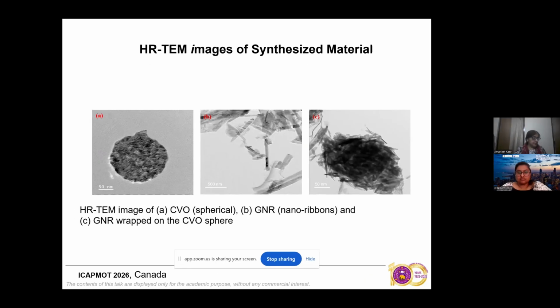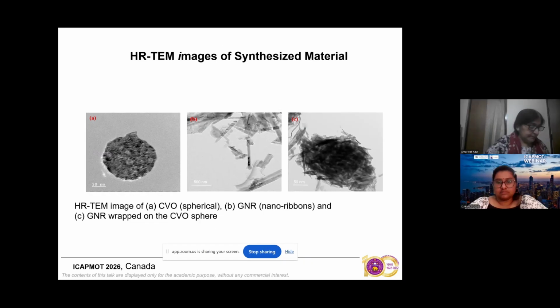So these are the HRTEM images of our synthesized material. You can see from these that the first is the cobalt vanadium oxide material, and the particles are spherical in nature. Then we have graphene nanoribbons. One can see that there are sheets of graphene nanoribbons which are wrapped around each other.